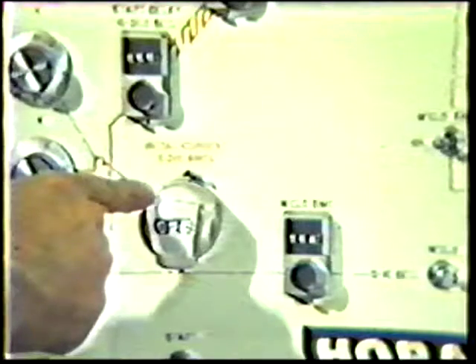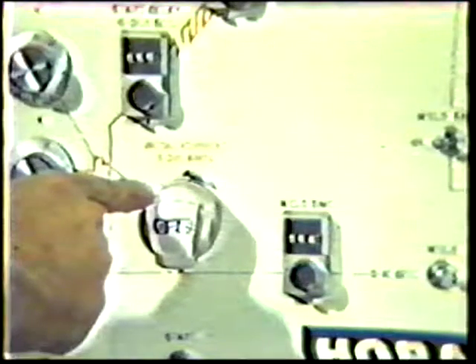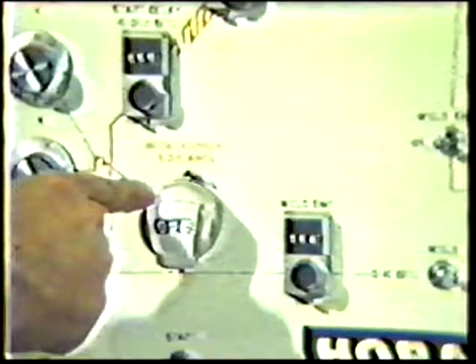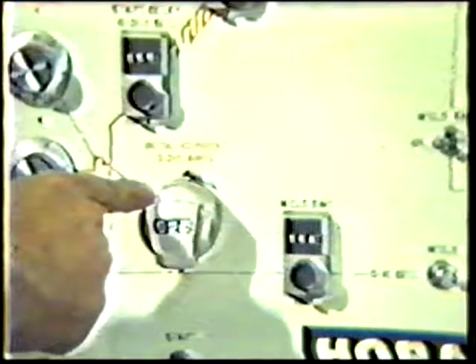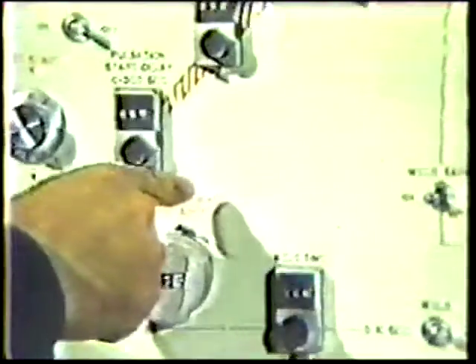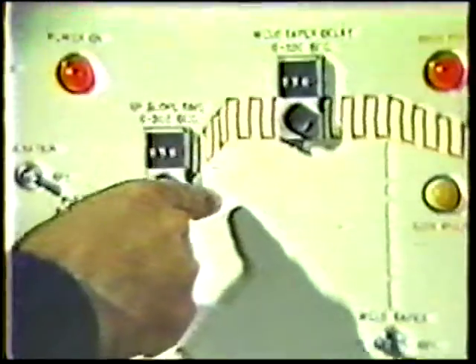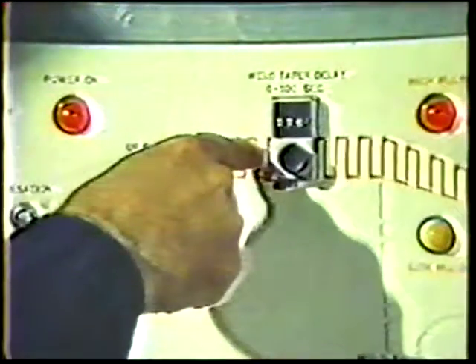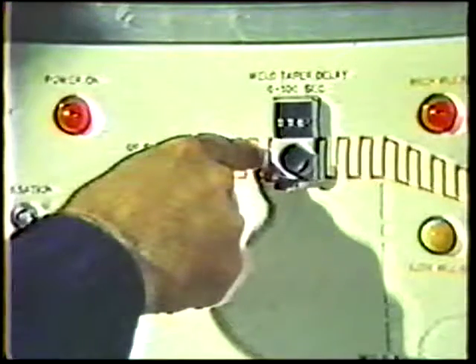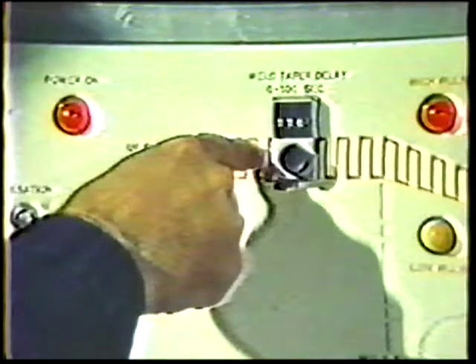When the arc is started, the current goes to the initial current, which is a minimum value relative to the welding current. The current then begins to upslope to weld current. This allows the current to increase gradually, producing a certain amount of preheating. Once the weld current is attained, welding begins as the torch begins its travel along the joint.